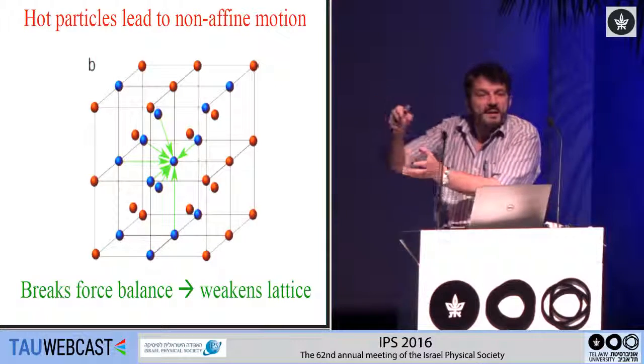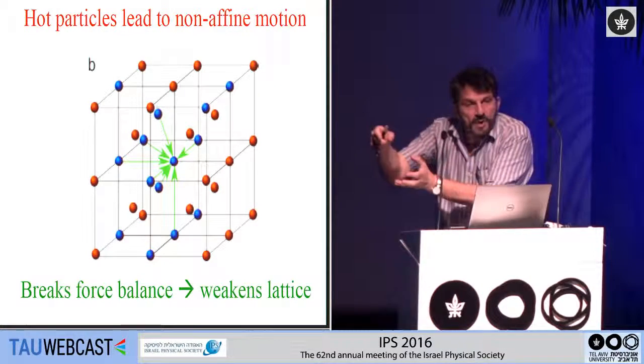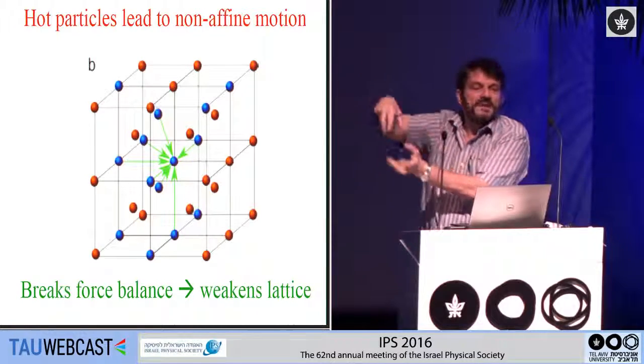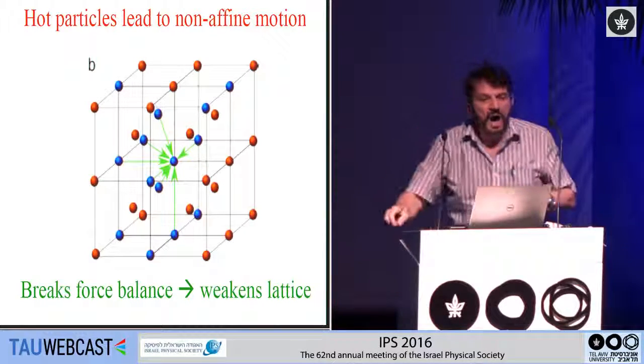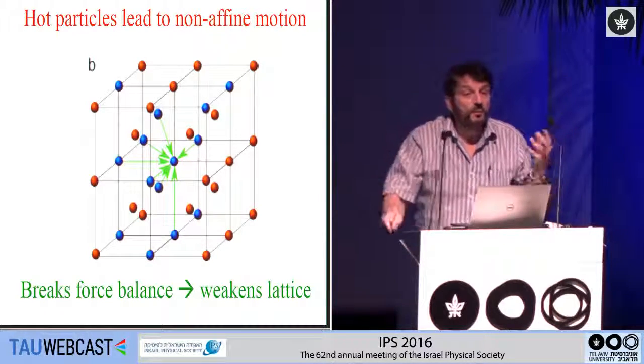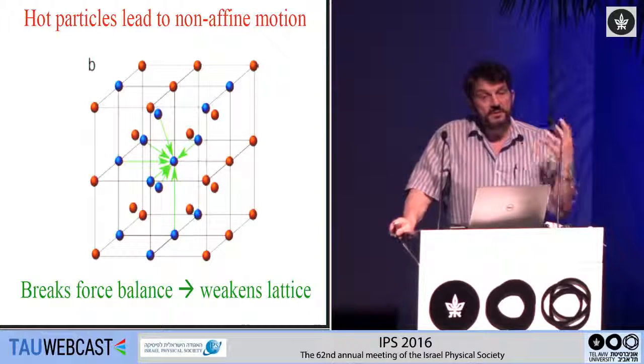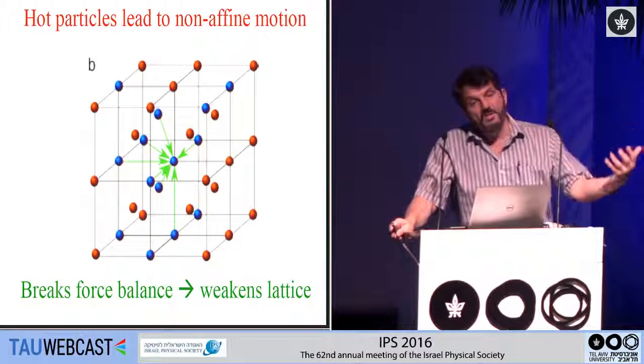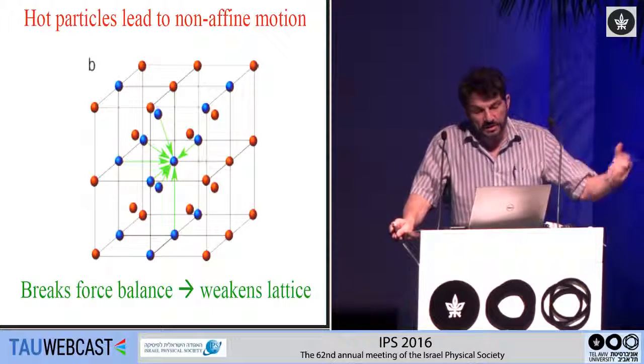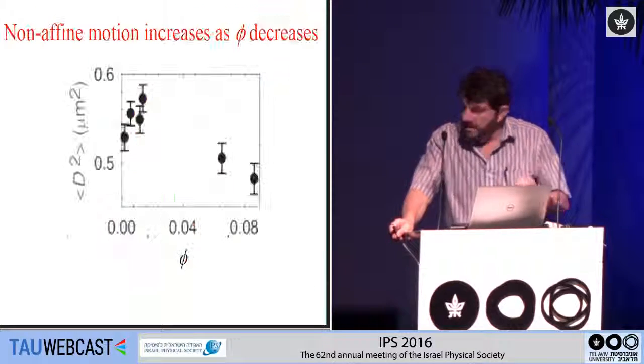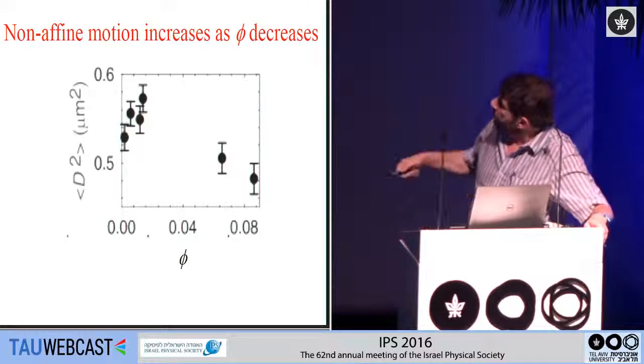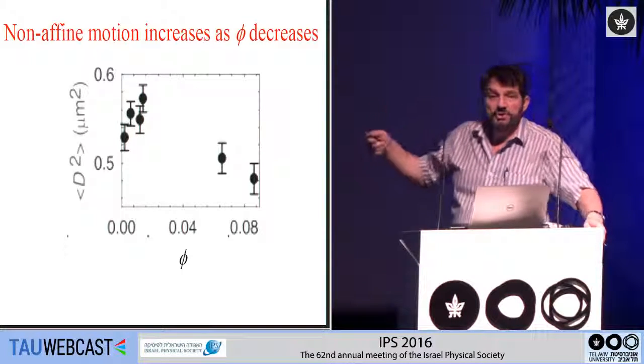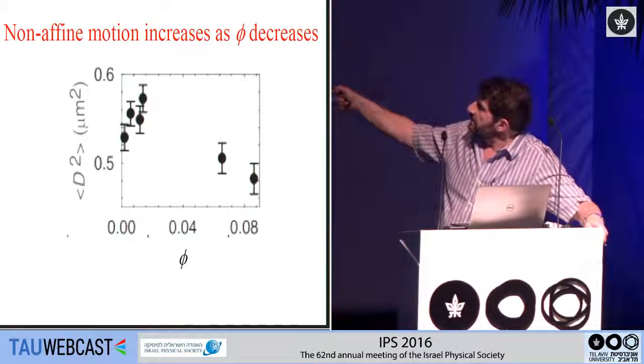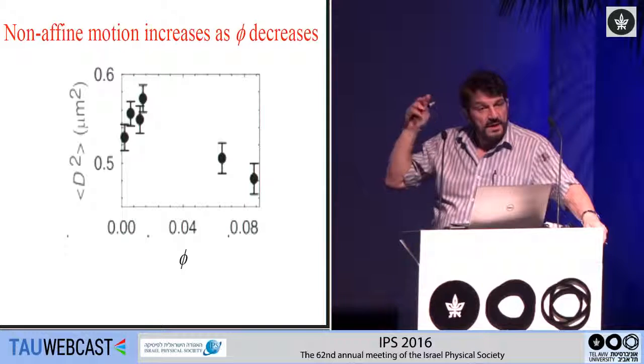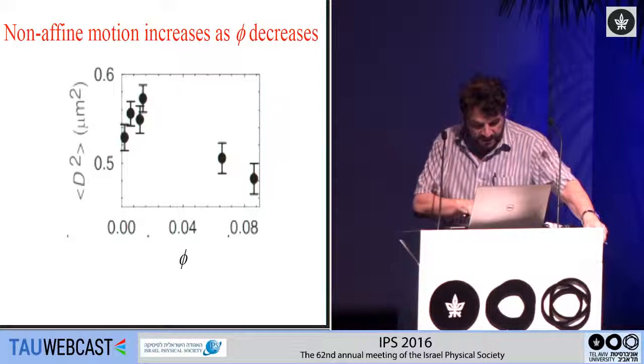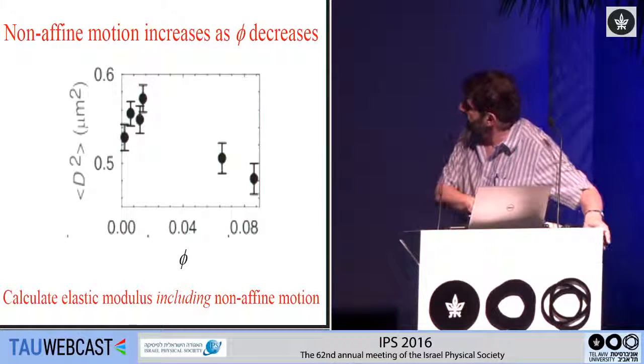You ask what the balance of forces is, and it disrupts the balance of forces, so the particles have to move to account for that. That also explains why these hot regions of neighboring particles are so strongly correlated in space. And once you do this, you can look at the non-affine motion of the particles, and you see that it peaks around the melting transition.